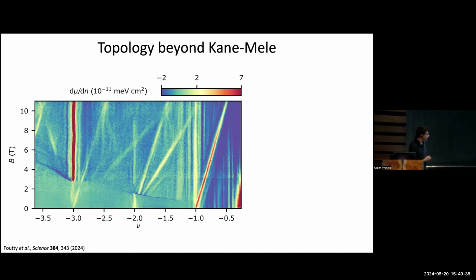Maybe in the interest of time, I'll just mention that we can do the same sort of mapping as a function of filling and magnetic field. Again, we see at high field some topological states. Again, you can see these sharp dark blue features that correspond to phase transitions, where the nature of the states changes abruptly. And basically, this defines a line where in the high field regime, we're fully polarized, like we talked about for the heterobilayer, and in the low field regime, we're partially polarized.